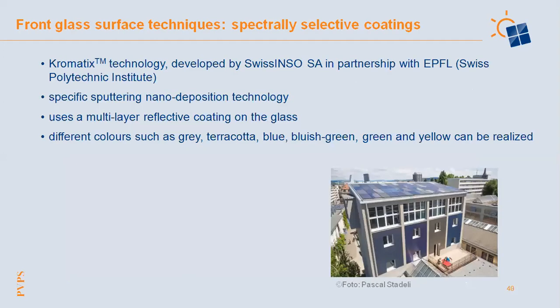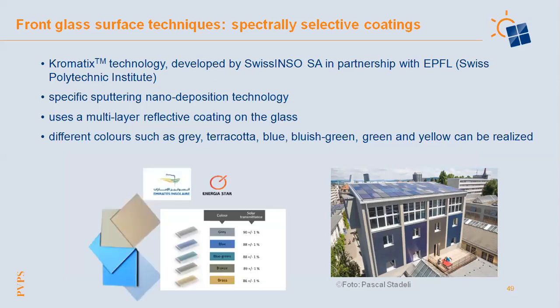So I want to start with the front glass, and which surface techniques exist to color the front glass. One possibility is to use spectrally selective coatings. The first one I want to show is the Kromatix technology, which was developed by Swiss Inso. They use a multi-layer reflective coating on glass. It is a specific sputtering technology, and you can have different colors such as gray, terracotta, blue, or green. As you can see in the small table I showed you here, the solar transmittance is still between 86 and 90%, so that's quite a lot. You don't lose too much by using these color codings.